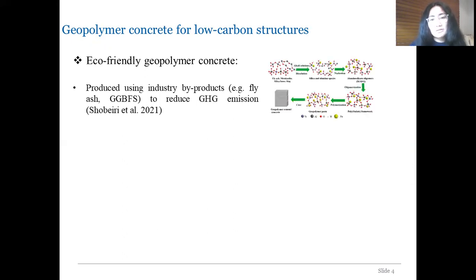The geopolymer concrete can be generated through the process shown on the right-hand side as a series of chemical reactions. So the geopolymer concrete was generated using the industry byproducts such as fly ash and GGBFS with aluminosilicate rich materials, and these materials are reacted with alkaline solutions to generate geopolymer concrete. The research performed by my colleague Philip has shown that the geopolymer concrete and its production leads to much reduced greenhouse gas emission in comparison with the Portland cement concrete.